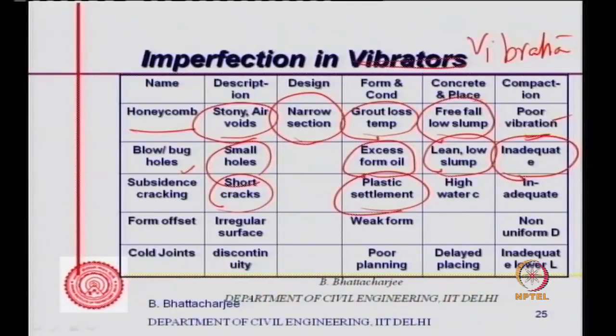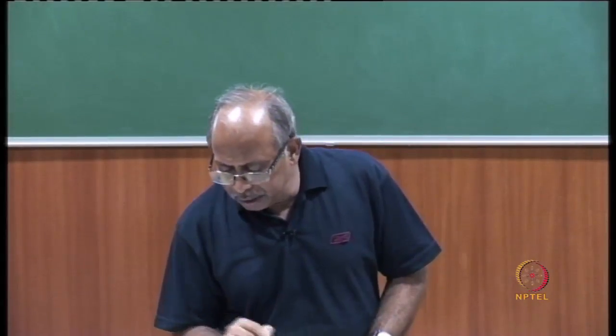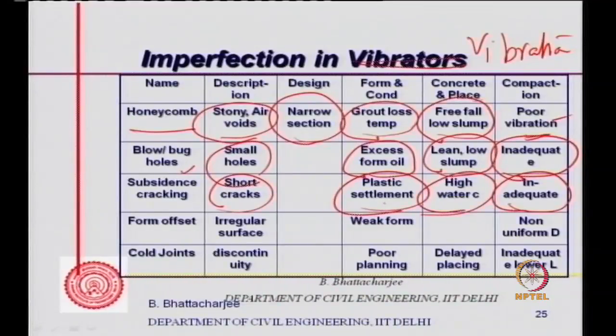Now, it's a bleeding concrete. This can occur in concrete which is bleeding, because the water comes up and the solid subsides. So this can happen, and inadequate vibration can result in this. High water content is usually the cause. So in concrete which has high water content, you might get short cracks. The cracks look like this, in fact.